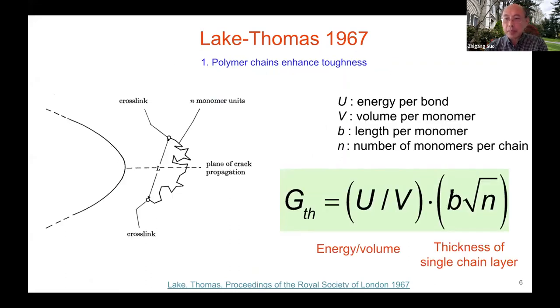This thickness is a square root of N times b. b is a length per monomer, and N is the number of monomers along the chain. You take the square root because the chain is going through a random walk. So this is the thickness of that layer. So this is energy per volume times the thickness of a single chain layer, and that gives you energy per area. That's how much energy you need.